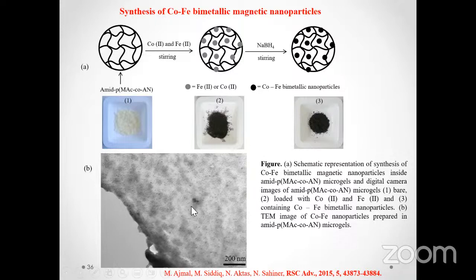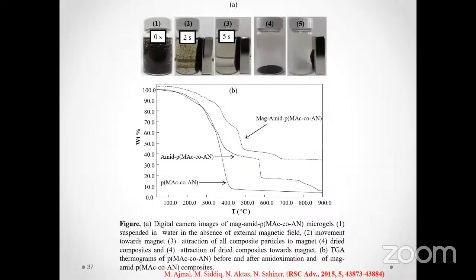And this TEM image again shows that this system was very effective for the preparation of well-dispersed bimetallic nanoparticles, homogeneous in shape and size, in this case. And then this bimetallic nanoparticle-containing hydrogel system was also used as an adsorbent. And it was observed that this system retains its magnetic properties even when dispersed in the reaction medium, or when present in water, or in the absence of water. No matter whether the hydrogel is in dried form, or it is suspended in any reaction mixture, it responds to the external stimuli.